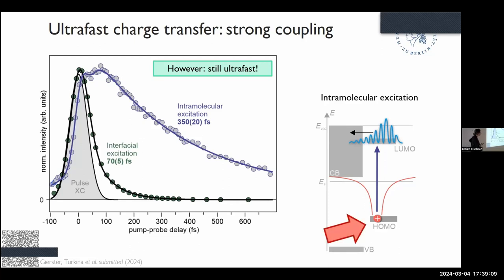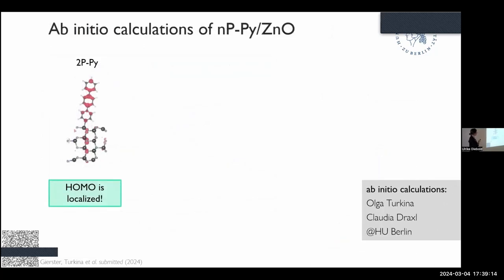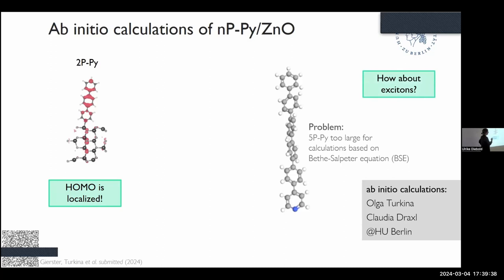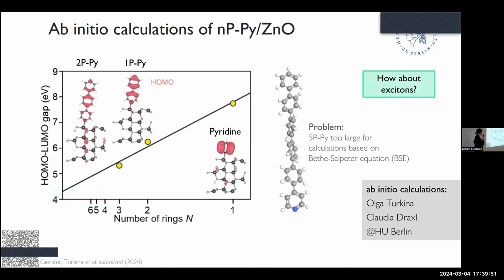So let's have a look at the HOMO. And what it looks like here, we collaborated with theory. These are ab initio calculations from Olga Turkina and Claudia Draxl. And they show, okay, we have a localized HOMO. And this is maybe not too exciting, but Olga and Claudia can also do Bethe-Salpeter equation calculations, which allow us now to look really at the optical excitations in complex systems. The problem is that the 5P pyridine is really too large if you want to add the zinc oxide to this. And so they kind of used a trick. As usual, also for the NP pyridine family, the HOMO-LUMO gap just scales with the number of rings, and this is actually not linearly, but here logarithmically.